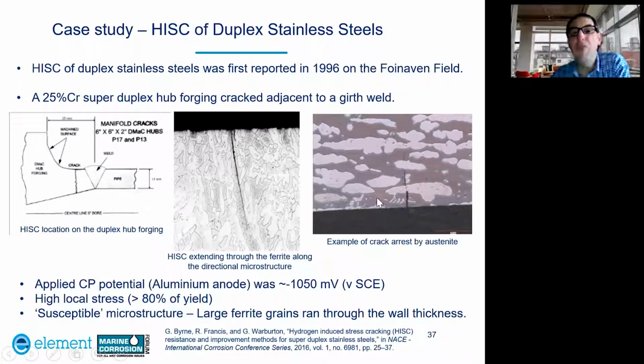This photograph on the right hand side is not from the failure, but I put it as an example to show how the directionality of the duplex structure and also the austenite spacing has a big influence on preventing HISC. And you can see here we've got a HISC crack that runs through the ferrite phase, is arrested by the austenite, then obviously is delayed, but in this example it finds its way around this austenite island, then continues through the structure, finds its way around this austenite island again, and then is terminated in this region.